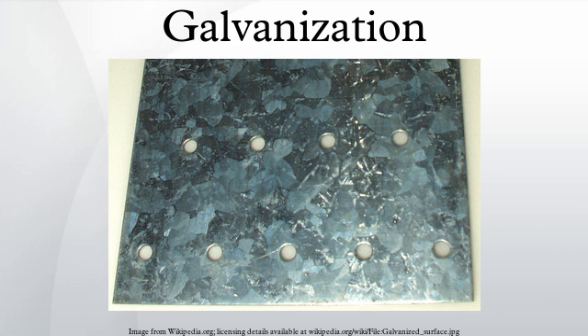Methods: hot-dip galvanizing deposits a thick robust layer that may be excessive. In the case of automobile bodies, where additional rust-proofing paint will be applied, a thinner form of galvanizing is applied by electrogalvanization. The hot-dip process does generally not reduce strength on a measurable scale, with the exception of high-strength steels where hydrogen embrittlement can become a problem. This is a consideration for the manufacture of wire rope and other highly stressed products.